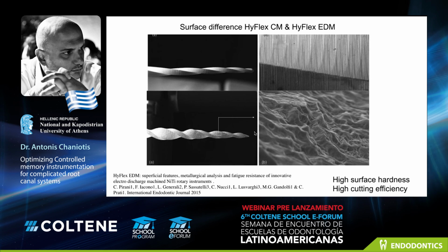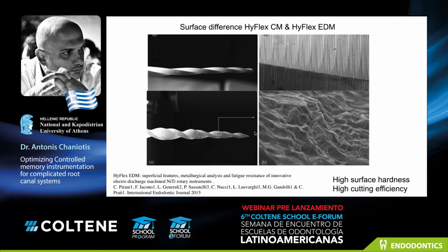Now, if you take control memory files and instead of grinding the flutes, you make the flutes with electrical discharge machining, what you will get is instruments of extreme surface hardness, extreme fatigue resistance, high angular rotation to fracture, and a higher austenitic finish temperature. But the torsional resistance will be similar to other files. And sometimes EDM files may also have lower maximum torque load to failure.